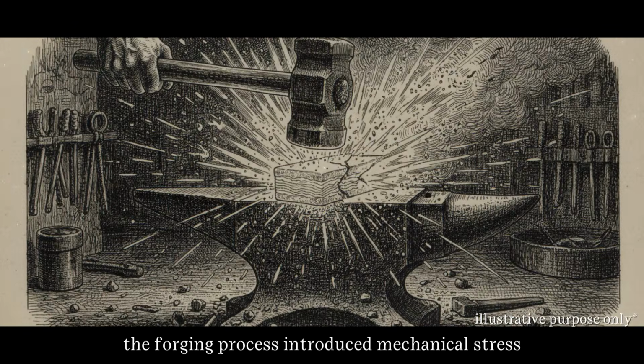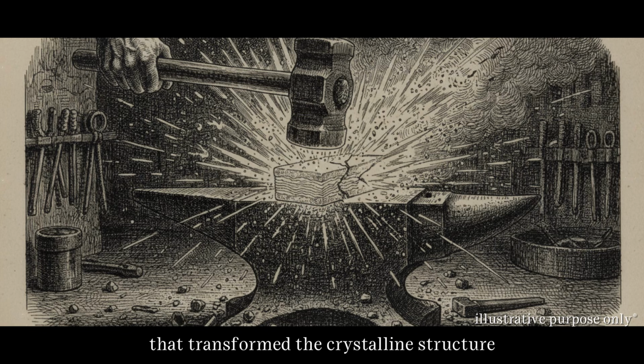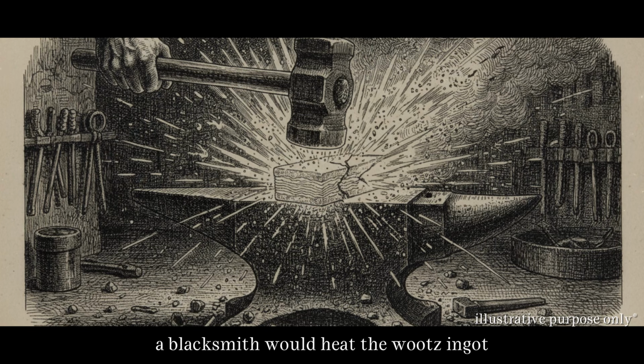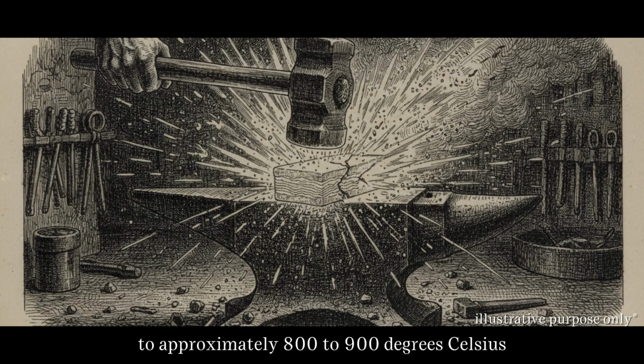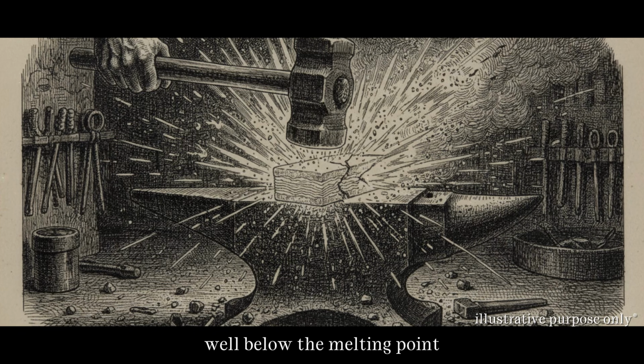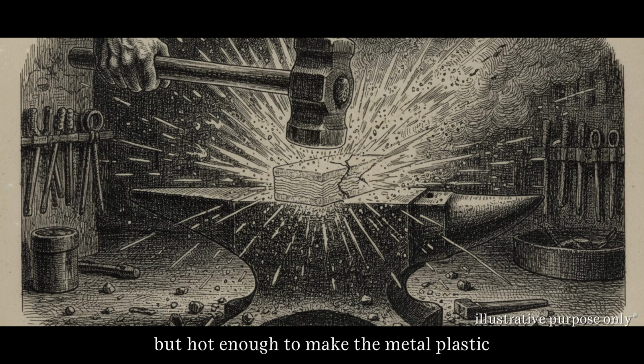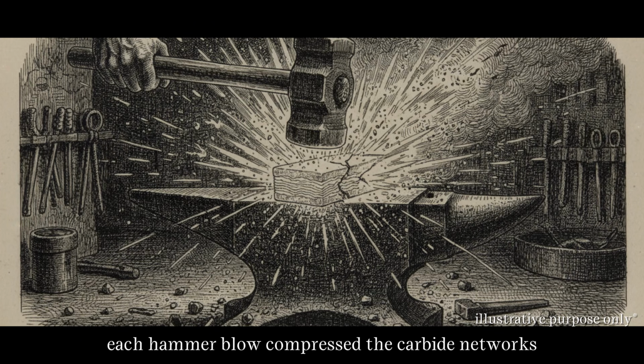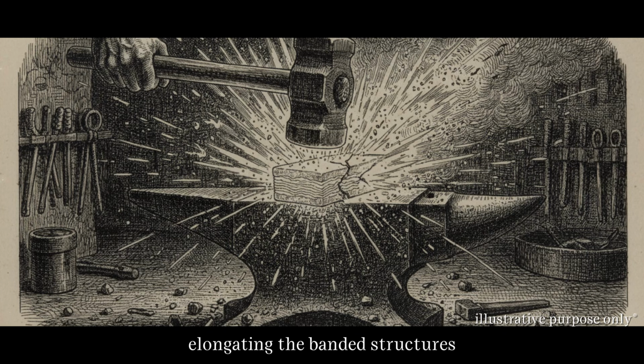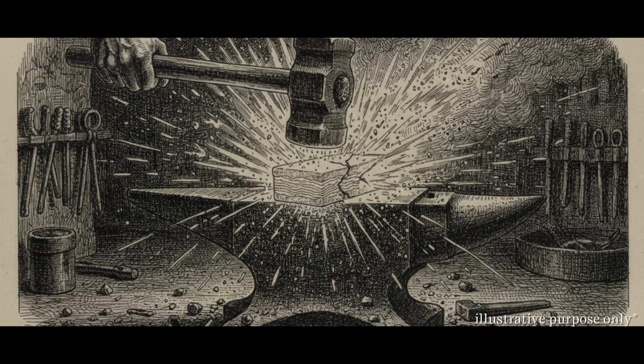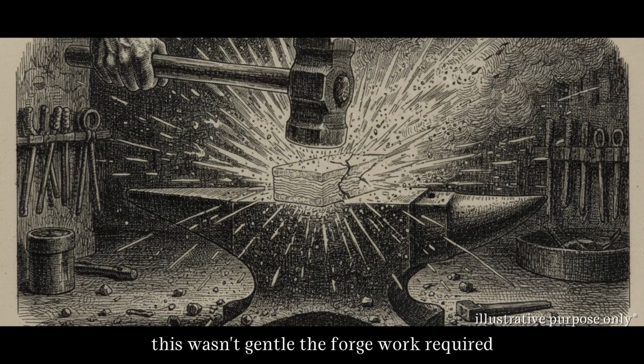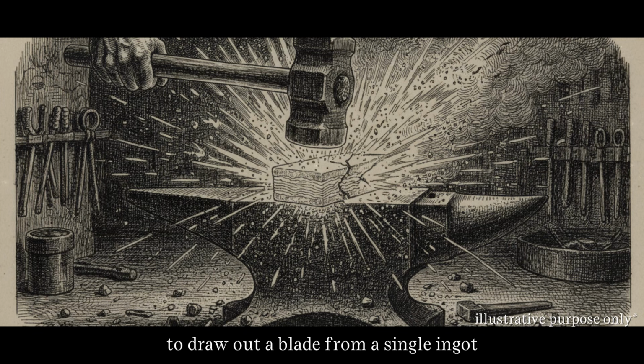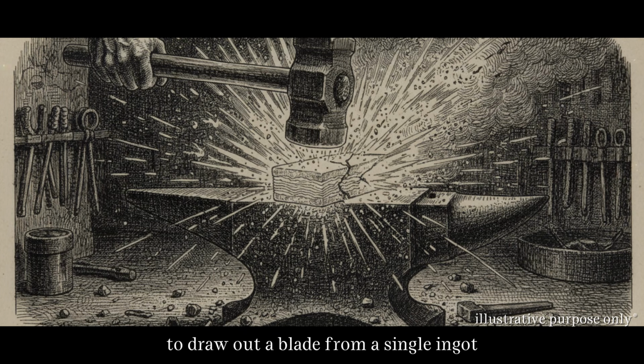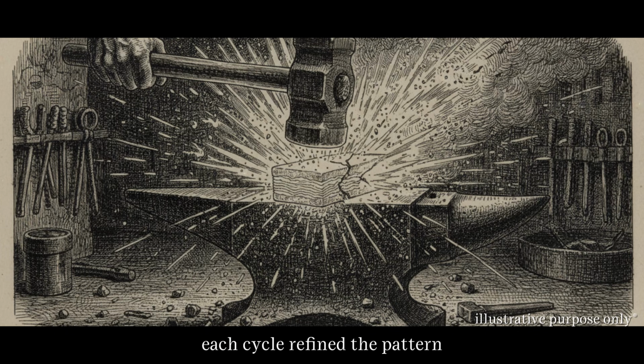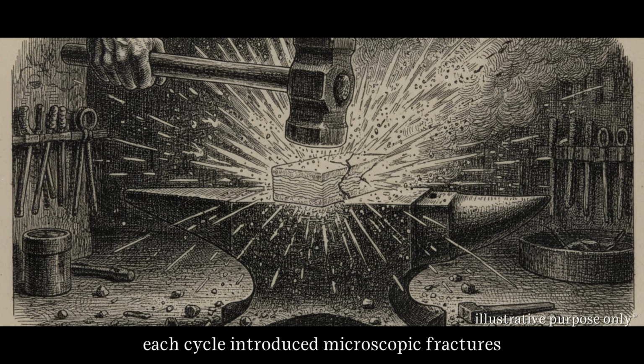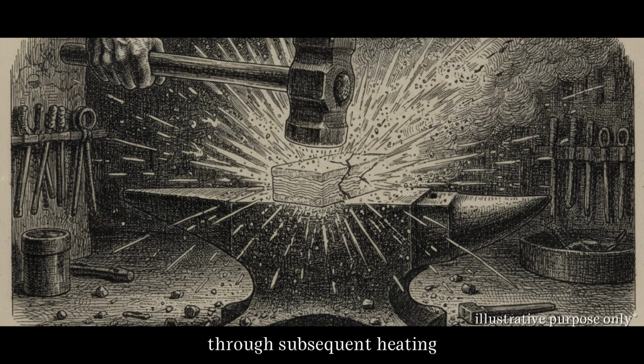The forging process introduced mechanical stress that transformed the crystalline structure. A blacksmith would heat the wootz ingot to approximately 800 to 900 degrees Celsius, well below the melting point, but hot enough to make the metal plastic. Each hammer blow compressed the carbide networks, elongating the banded structures along the direction of working. This wasn't gentle. The forge work required dozens of heating and hammering cycles to draw out a blade from a single ingot. Each cycle refined the pattern. Each cycle introduced microscopic fractures that had to be welded shut through subsequent heating.